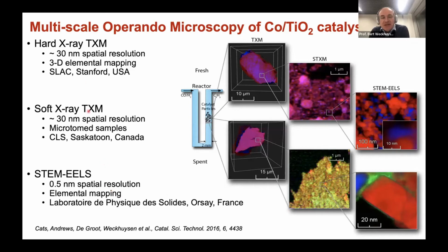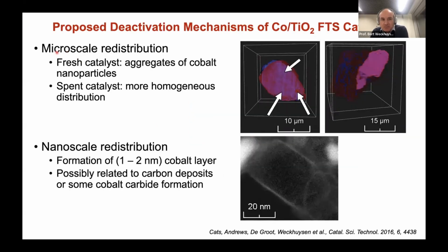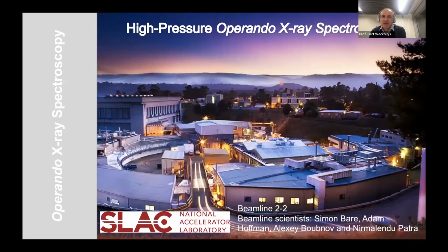Why I'm saying so? Because now I have to cut a long story short. We did hard X-ray, soft X-ray, which I discussed before, STEM-EELS, I will not dwell on it. And here I show you fresh and after catalysis. And that greenish is actually a carbon deposit. And here also you see changes. What is happening? You have a microscale redistribution and a nanoscale distribution, where you have carbons which are depositing. Remember these aromatics which I already showed you before in the STXM. But also, maybe less obvious from the STXM, if I would show you the 3D image, you see also migration. So you see microscale redistribution of cobalt and nanoscale redistribution taking place during catalysis.